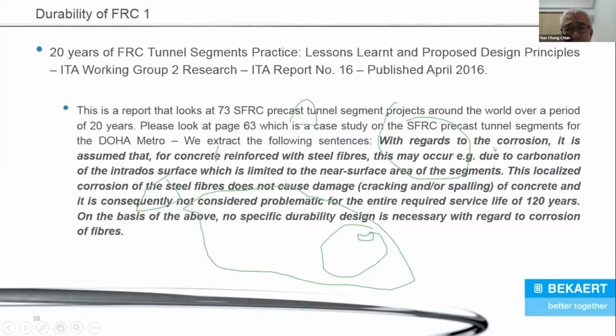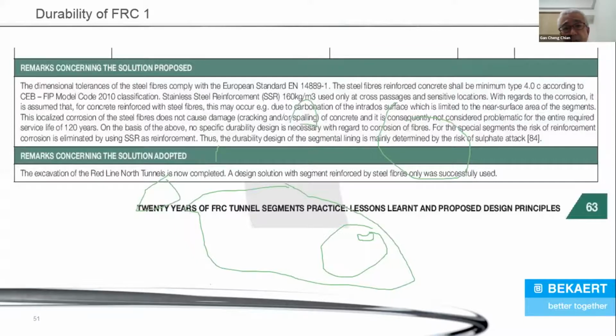With regards to the corrosion, it is assumed that for concrete reinforced with fibers, this may occur due to carbonation of the intrados surface, which is limited to the near surface area of the segments. This localized corrosion of the steel fibers does not cause damage, cracking and/or spalling of concrete, and it is consequently not considered problematic for the entire required service life of 120 years. On the basis of the above, no specific durability design is necessary with regards to corrosion of fibers. So this is confirmed by ITA Report 16, published in 2016. And this is just an extract from the same document.